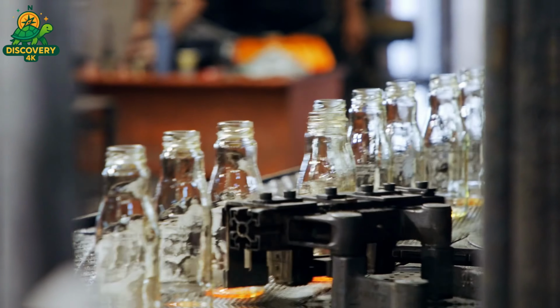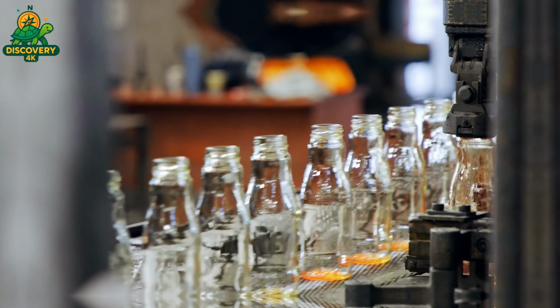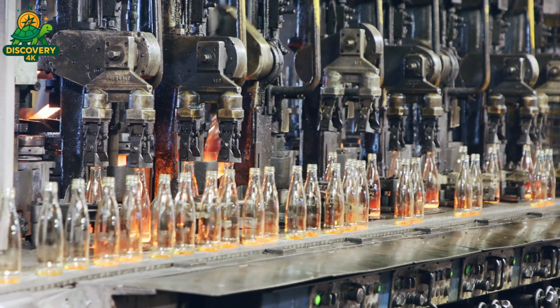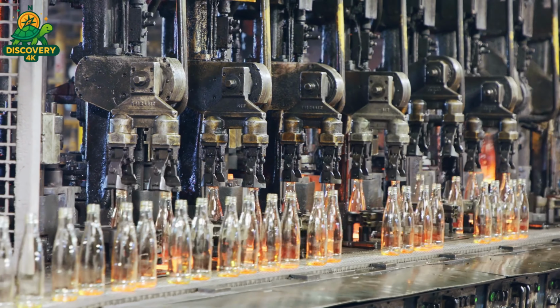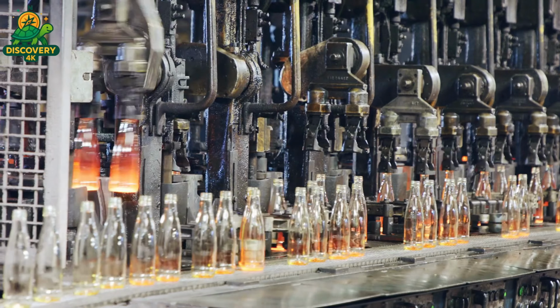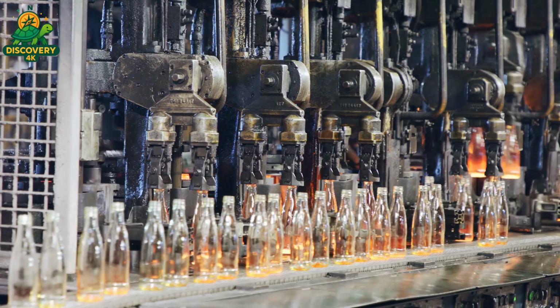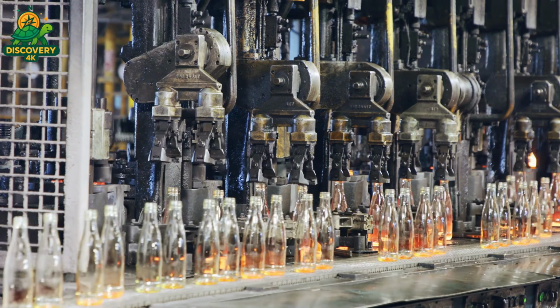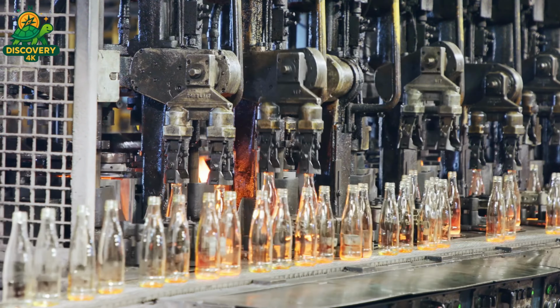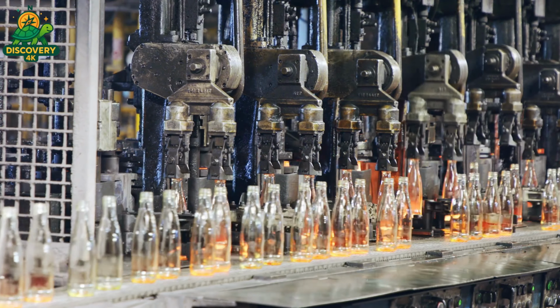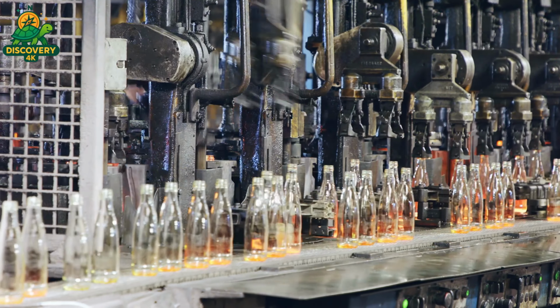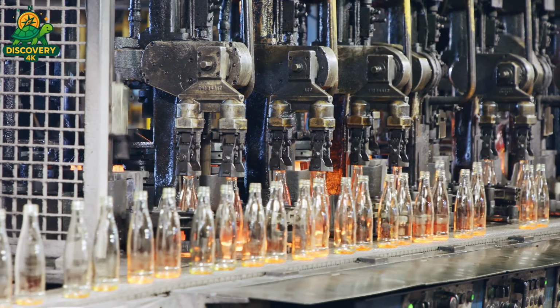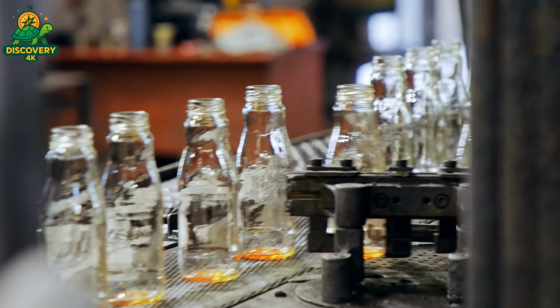Freshly molded bottles may look finished, but they're far from ready. Right after forming, the glass contains internal stresses caused by uneven cooling. Left untreated, these stresses can cause bottles to break spontaneously, even days later. To solve this, the bottles enter a process called annealing, which carefully relieves stress and stabilizes the glass structure. They pass through a long tunnel oven called a lehr.